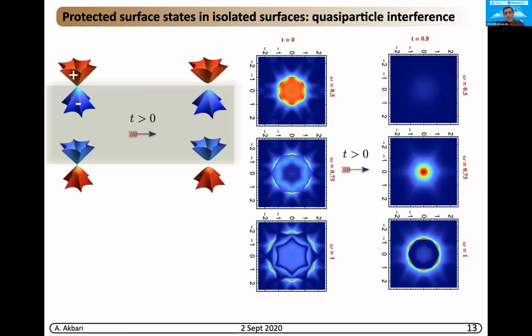Now, if we go to higher hopping, you see that the effect of the gap appears in the system at lower energy, where the energy is less than T. We don't have any spectral function, therefore we don't see any trace of the QPI. But if you go to higher energy, then you see that it starts from the drop-like feature and shows a similar fashion at the higher energies.